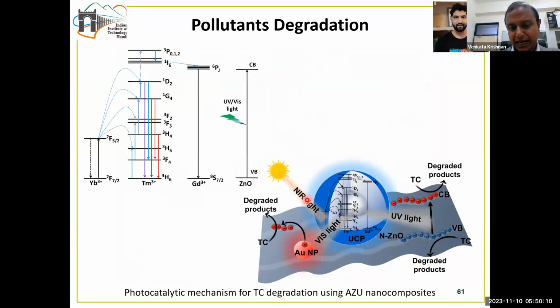So especially when this NIR light is falling onto this upconversion nanoparticle, so we have this core shell type of upconversion nanoparticle, and due to the nonlinear optical processes which are involved in this upconversion, it emits the visible light and also the UV light. The emitted UV light is absorbed by this N-doped ZnO, which is shown here in this wavy structure. This is absorbed, and that leads to the promotion of an electron from the valence band to the conduction band, and that leads to the degradation of this pollutant tetracycline.